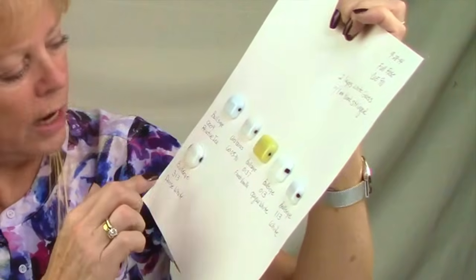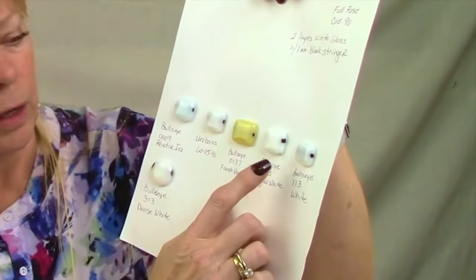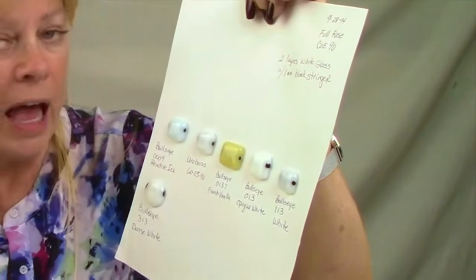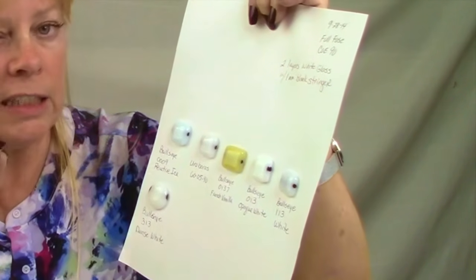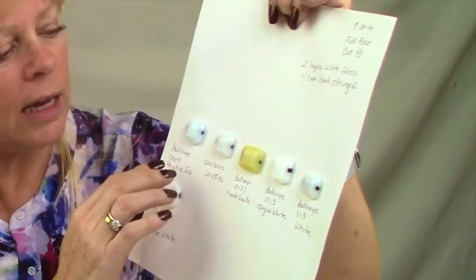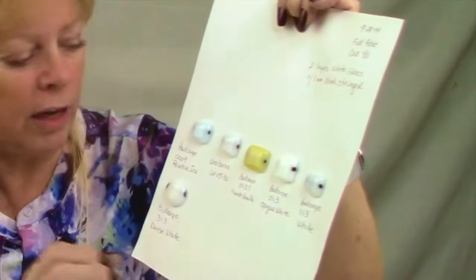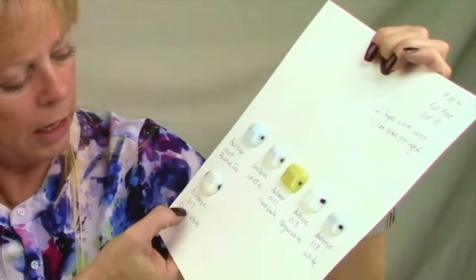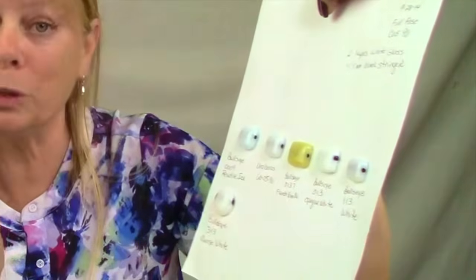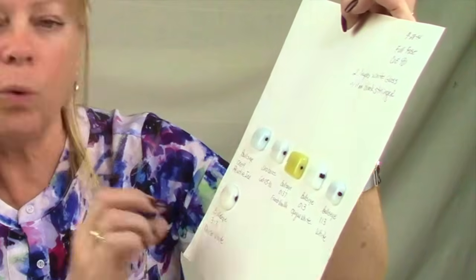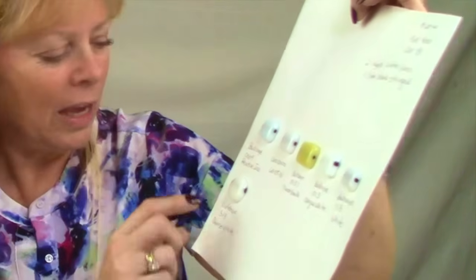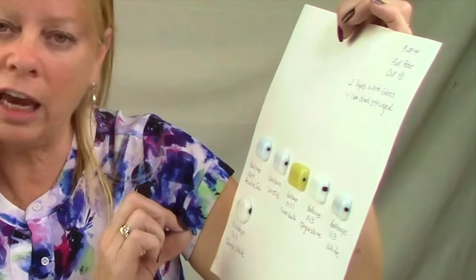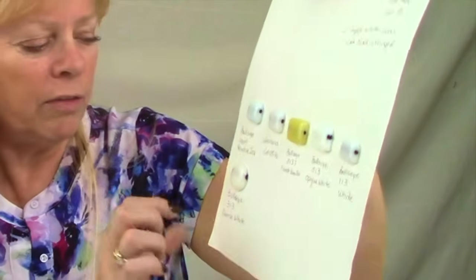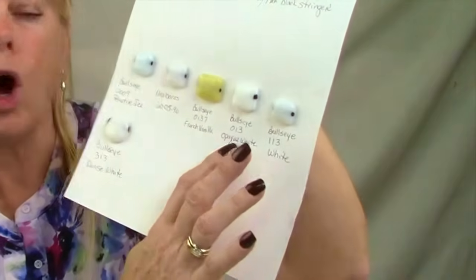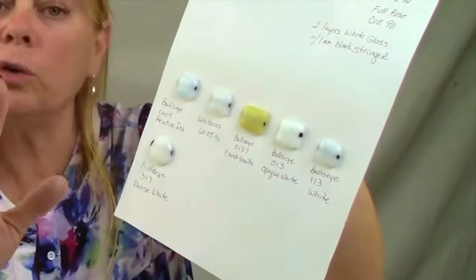And it turned out that 013 opaque white was the densest. I couldn't see the black stringer very well, so it was a very dense color, very opaque, and it was the brightest white that I could find. I did notice that sometimes on the 313 dense white, actual dense white, it wasn't as bright as 013, and sometimes I get devitrification. It's a very difficult glass to work with. So even though it says dense white, I go with opaque white. That's my favorite. You can do your own test.